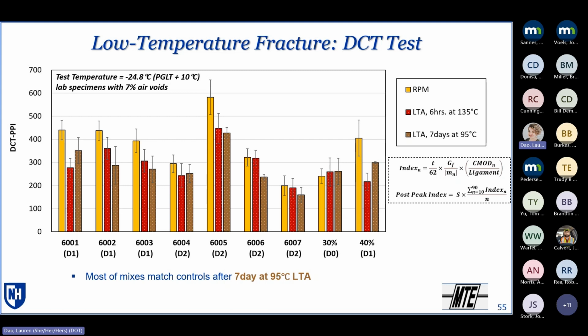And again, with these, we're not testing field cores, but we have the reheated plant mix and the 2 long-term aging conditions. The test temperature with these corresponds to the test temperature at the site location plus 10 degrees C. And again, all of these are 7% air voids.